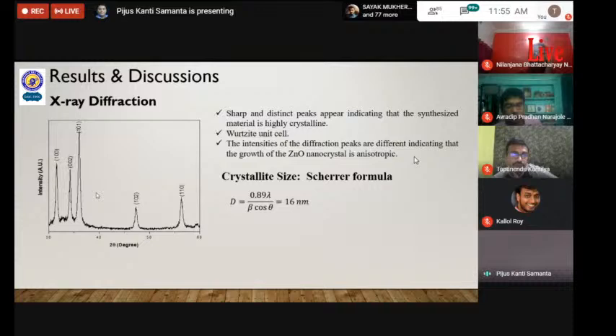In fact, by crystallite size, we mean here the coherent domain participating in diffraction of X-ray. And we used the Scherrer formula to calculate the particle size, where this beta is the full width at half maxima of the peaks and theta is the corresponding diffraction angle. And we considered the highest intensity peak for this calculation. This calculation shows that the crystallite size is 16 nanometer, which is very small.